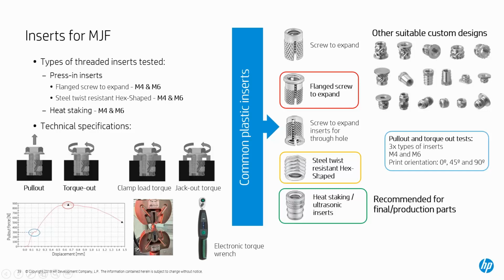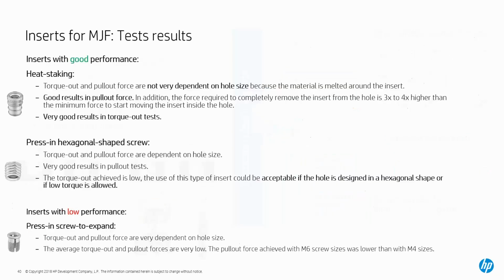You can print threads with MJF. You can go down to M4 or M6, and they work fine, whether you print in the 90-degree orientation or 45-degree orientation. But when you need a stronger thread or a tighter thread, depending on how much screwing in and out you're going to be doing, we would recommend an insert. It depends on the application, but the best results that we've found are through heat stake inserts. They have the best torque out as far as the parts because you're essentially melting that insert into it.